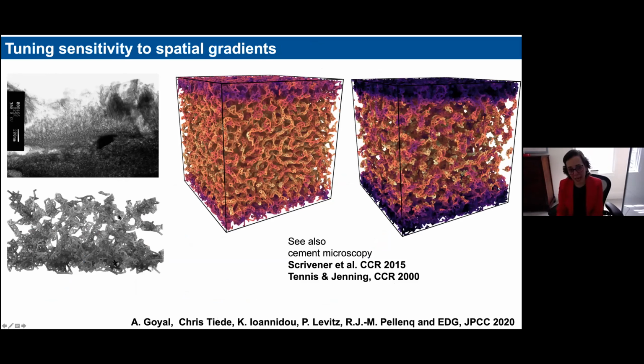The last thing that I want to say is that in this type of simulation, we can actually now introduce a more complicated pathway for the kinetics of gelation, because this is a TEM image of the gel formation that you can see. It starts from the surface of the grain, and there are gradients of density departing from the grain that is dissolving, as we would expect. So we can modify this simulation to mimic this type of gradients.